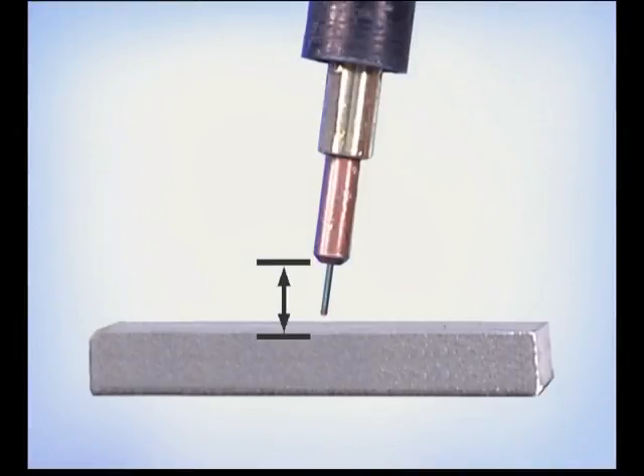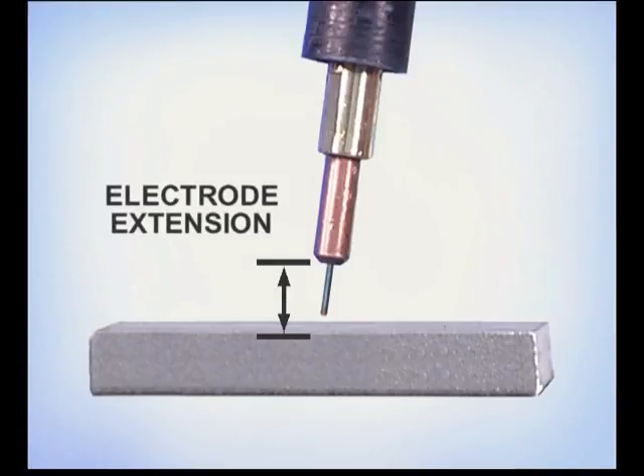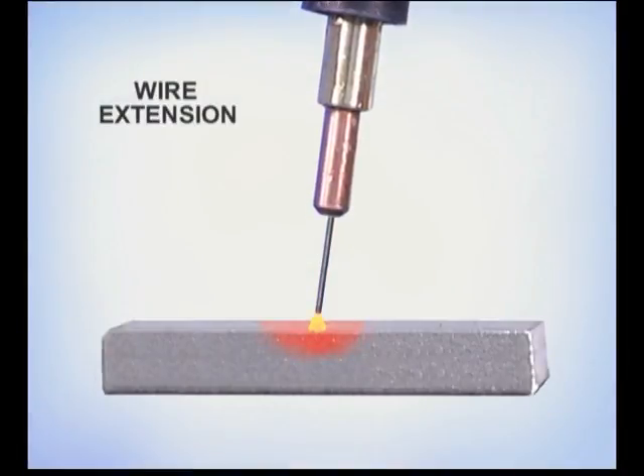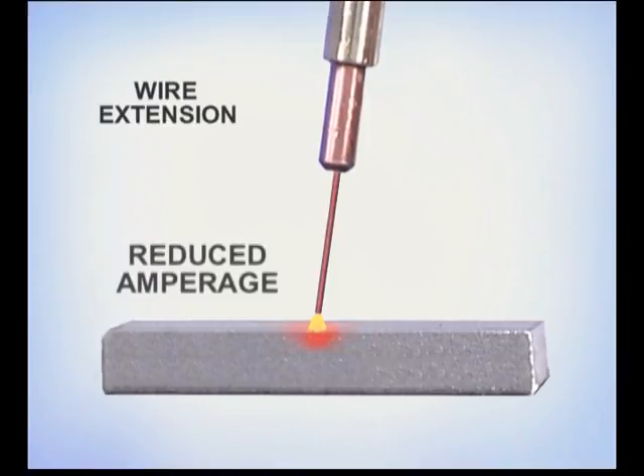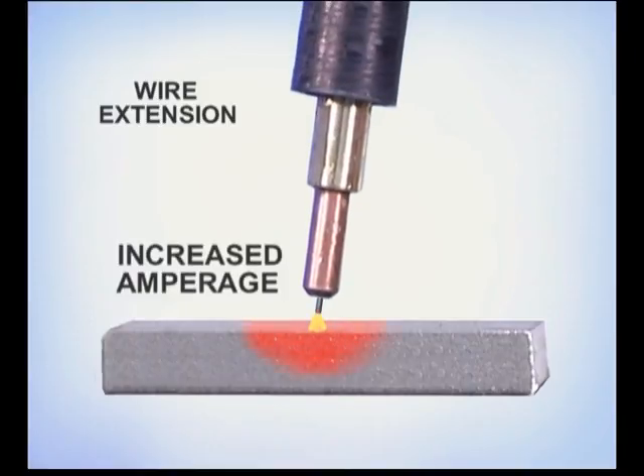Even though the welding machine does automatically maintain the arc length, the amount of wire that sticks out from the end of the contact tip to the metal, called electrode extension or wire stick out, will affect the amount of heat at the weld. CV power sources try to maintain a constant voltage, then provide the amperage necessary to burn off the wire. Longer electrode extensions allow the wire to preheat, reducing the amperage necessary to burn it off and reducing the heat at the weld. Shorter electrode extensions cause the amperage and heat to increase.